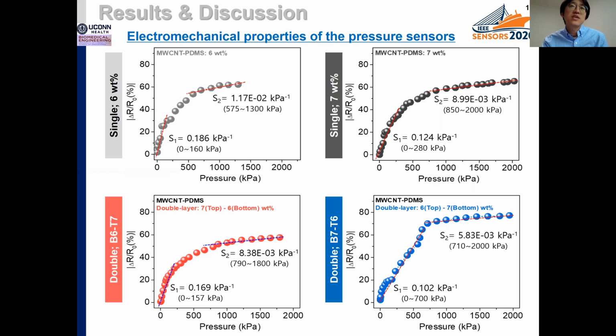The results indicate that top-high and bottom-low concentration alignment makes the pressure sensor show a gradual change in resistance under pressure change, which means that the order of alignment for the stacked double layer sensor is an important factor to achieve higher linearity and a wide pressure range.